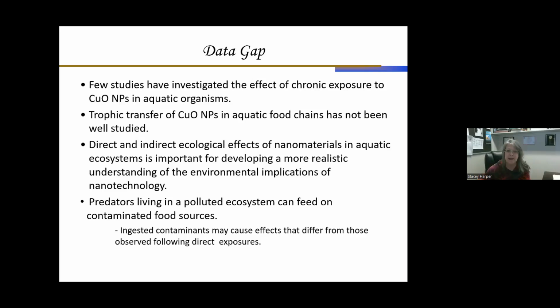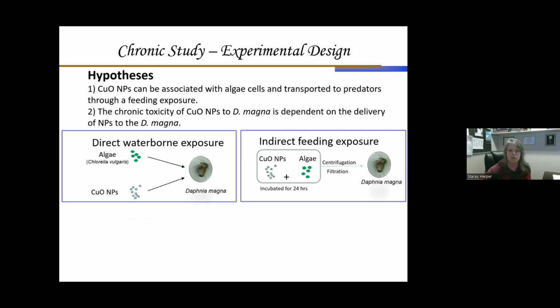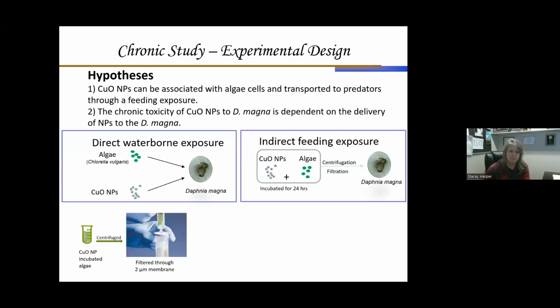And we predicted that they might have differential effects if they're exposed through their prey versus just exposed in the water column. So we set up, based on a couple of hypotheses that we had, that the delivery might alter the toxicity of the materials. We had a direct waterborne exposure where we just fed algae and copper oxide nanoparticles to Daphnia at the same time. And we had an indirect feeding exposure where we pre-incubated the copper with the algae and let that incubate for a while, and then centrifuged them and collected them.